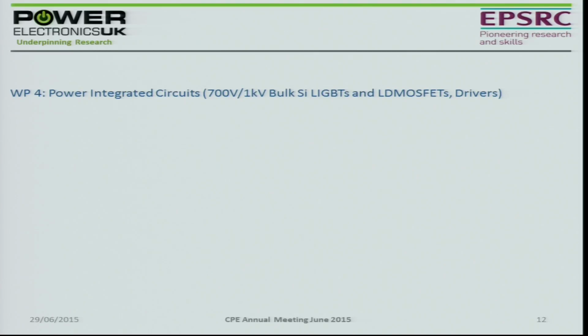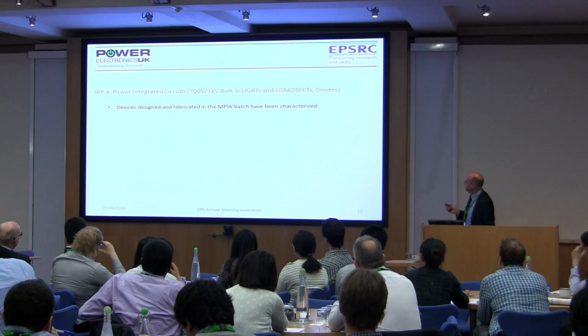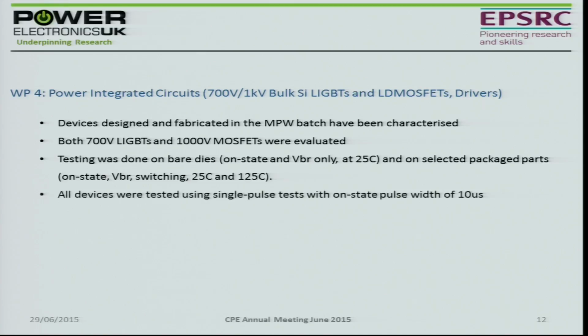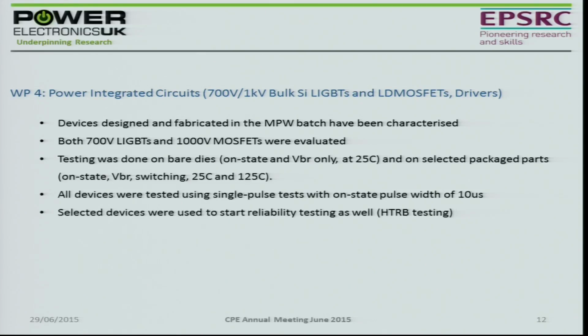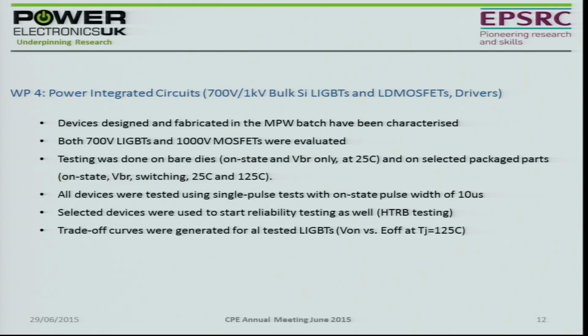So work package 4 that Cambridge are also working on is on these 700 volt, 700 V to 1 kV bulk silicon lateral IGBTs and MOSFETs. They've been, again, fabricated at a foundry externally and characterized. The bare dies have been tested at different temperatures and different switching speeds. All the measurements are pulse tested. Some devices have started to have some reliability measurements done on them, and similar to that previous slide, the trade-off between the V-on and the turn-off energy are being compared.